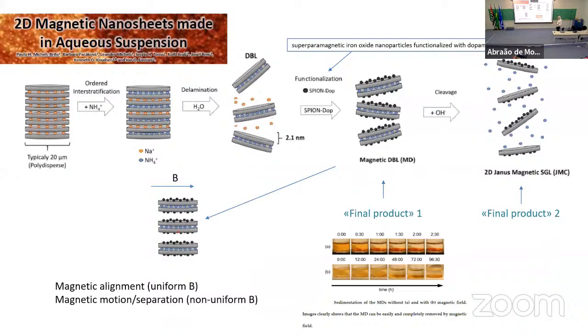This is the last poster we had in Boston. In this case, we have actually intercalated magnetic nanoparticles in the clays. And what we can do by this ordered interstratification process, we can produce two kinds of products. We can produce nanosheets, double layer sheets with magnetic particles on both sides. We can delaminate that, and we can create suspensions with one layer of clay with magnetic particles attached to one side.